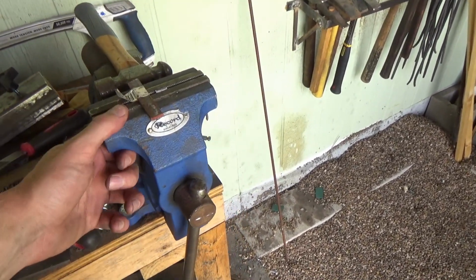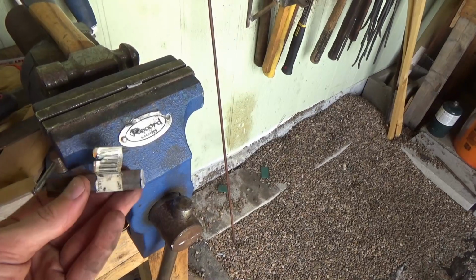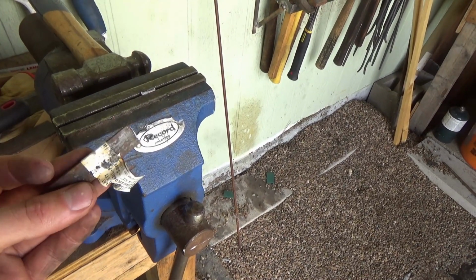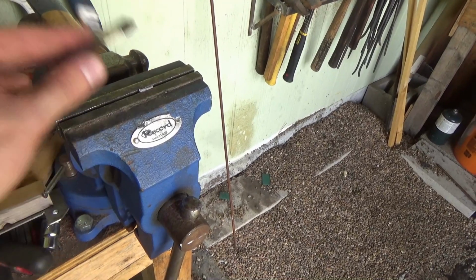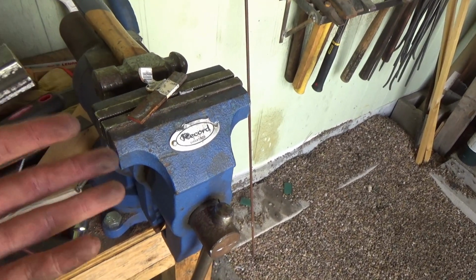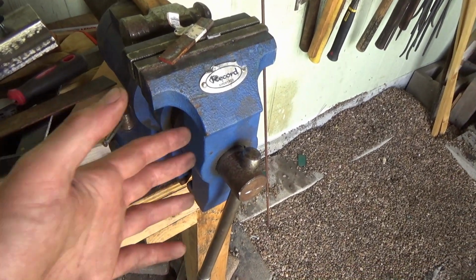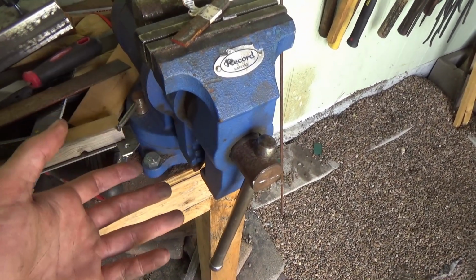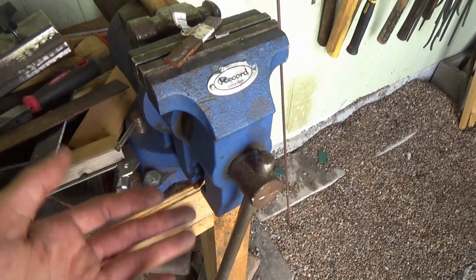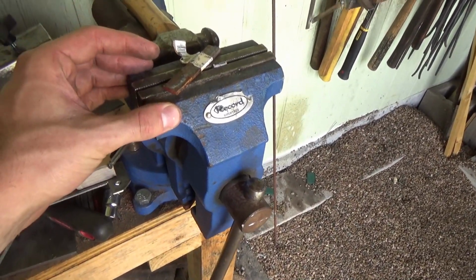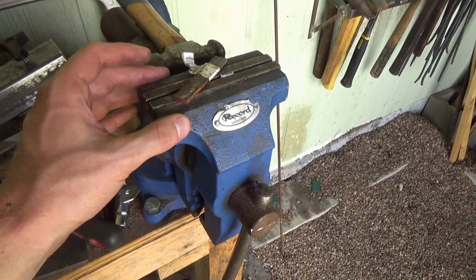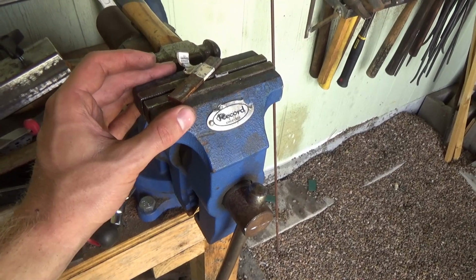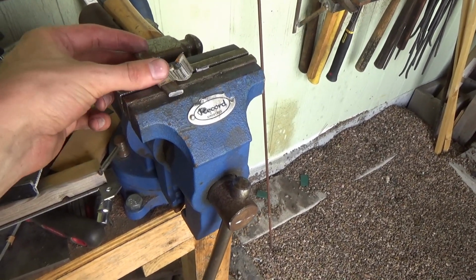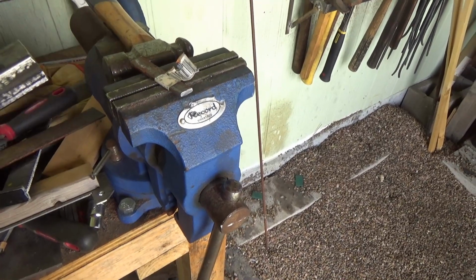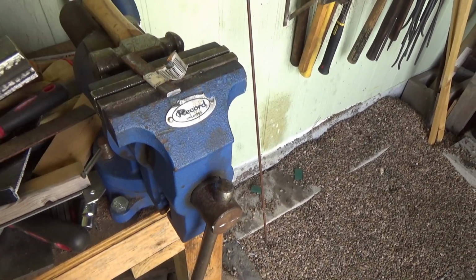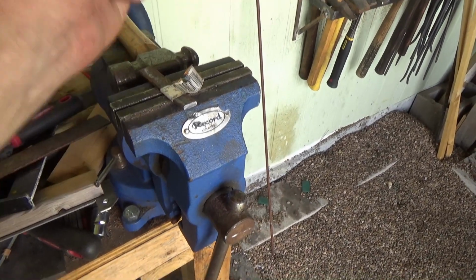I could talk about cast iron, similar to how it can't be work hardened, or how that's not a good thing. And the same reason as to why it's very bad with work hardening. You can't really weld it that easily. Yes, it can be welded. Duh, almost anything can be welded. But cast iron is difficult to weld, especially if you don't have much money, you don't have many tools, you don't have much experience, for the same reason that work hardening would be a very, very bad thing. All the carbon that's in it, all that carbon that settles out of solution as pure graphite.